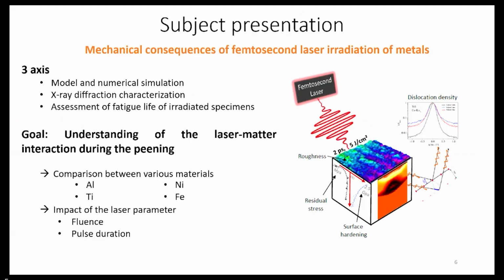For this work, we are working on three main axes. First, modeling and numerical simulations in order to understand the creation of the shockwave and how it propagates. The second axis is experimental and includes characterization of peened samples thanks to XRD techniques. The third axis is the assessment of fatigue life with micromechanical tests. The goal is to understand how the metals interact with the lasers during the peening. To do so, we are comparing materials, including aluminium, nickel, titanium, and iron, and the impact of the laser parameters on this peening, which are fluence and pulse duration.